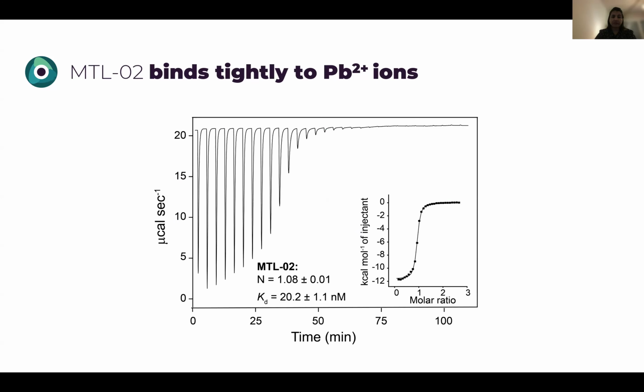And the reason for this is, again, metal affinity and metal selectivity. For example, in the case of MTL2, we checked the affinity to bind lead-2 ions, and the affinity is within the low nanomolar range, which is significantly higher than the affinity of the different standards of care. When we compare, it's important to mention that the methodology is very critical when we measure affinity.